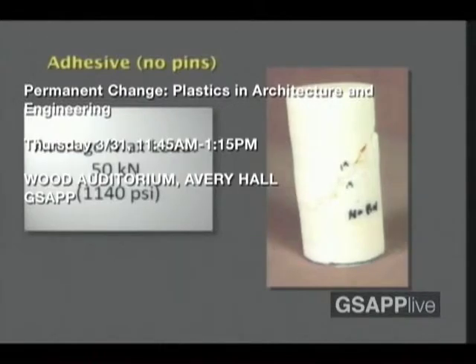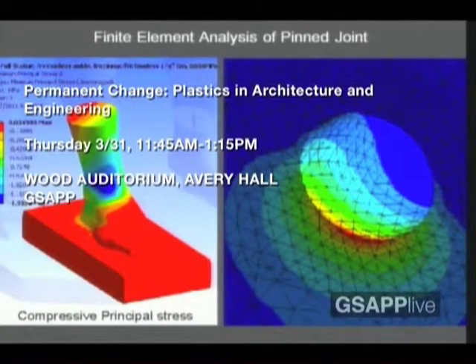This is 9 kilonewtons higher than the pin strategy. The pins actually, as we learned from doing finite element analysis, introduce stress concentration around the holes and actually cause the thing to be more susceptible to breaking than if you just glued it together with a thermoplastic resin. And just to address the final point that Michael talked about, how long do flexible materials last,